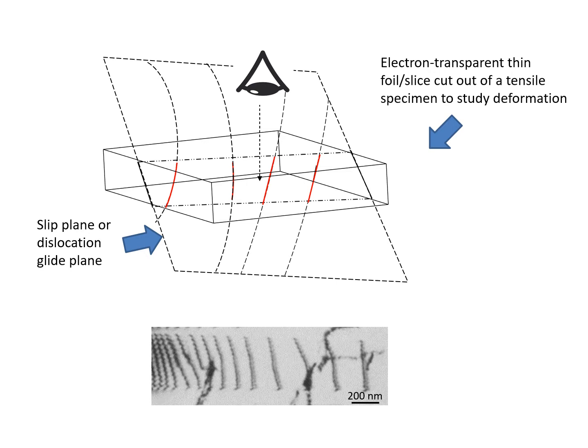It has no meaning until you've created the thin foil and created this imaginary intersection of the slip plane with the thin foil surface. So in the bulk, it has no meaning at all. But it might show up, and people might think that it actually corresponds to something real, but it doesn't, because it's an artifact of actually selecting your slice.